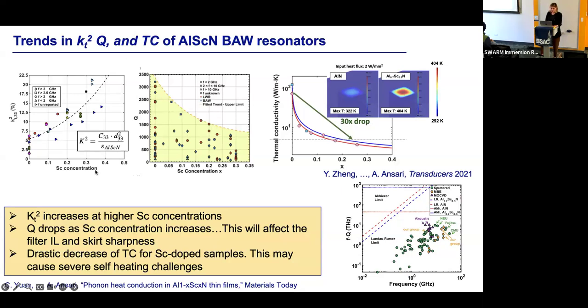All right, so let me just show you some of the trends in the Q, KT squared, and thermal conductivity of aluminum scandium nitride materials. As I explained, the nice thing has been that the KT squared increases a lot just because the d33 goes up, right? However, if you look through literature, and this is work by a lot of research groups, not just us, the Q of the resonators is decreasing with increase in the scandium concentration.